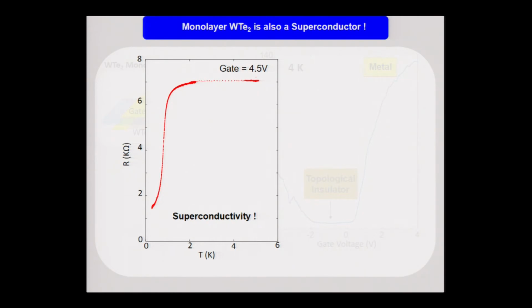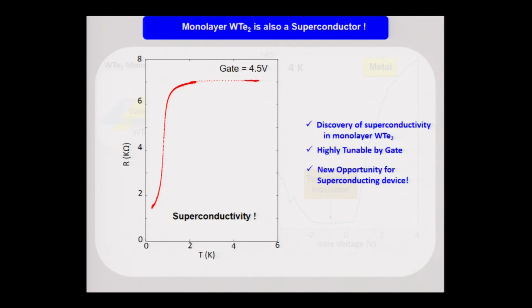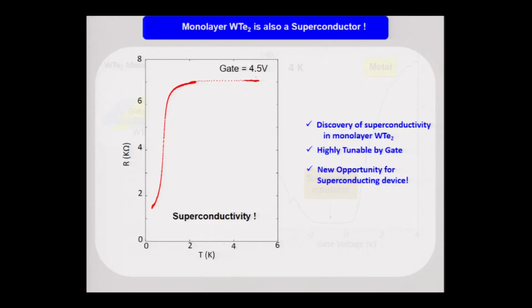Despite that, this number here is not going to 0 yet. That's because of a known imperfection in our current device, and we're currently working on a new device to remove the imperfection to see the real zero. But as a summary here, I want to say we discovered superconductivity in monolayer tungsten ditelluride, and it's very gate tunable because, as I said before, it's tuned from insulator to a superconductor. Like in a normal transistor, you tune from insulator to metallic state. Here, we tune from insulator to superconductivity. So I think it's a very remarkable discovery, and it provides a lot of new opportunity for superconducting devices. But I'm not going to talk in this direction.